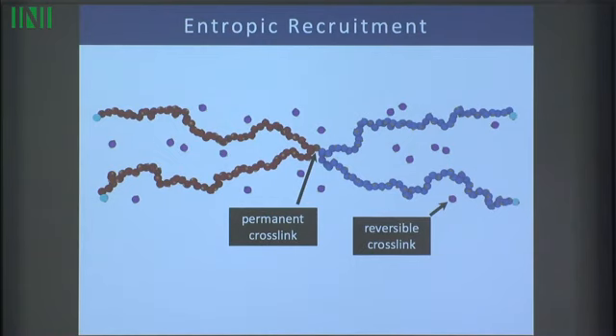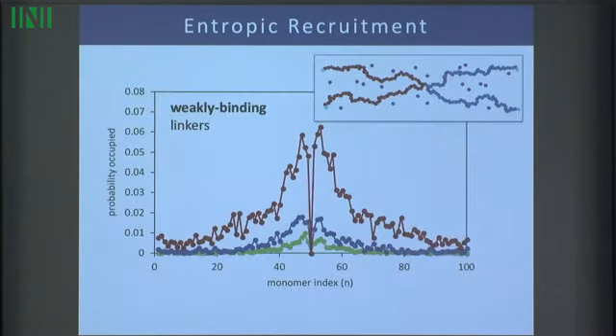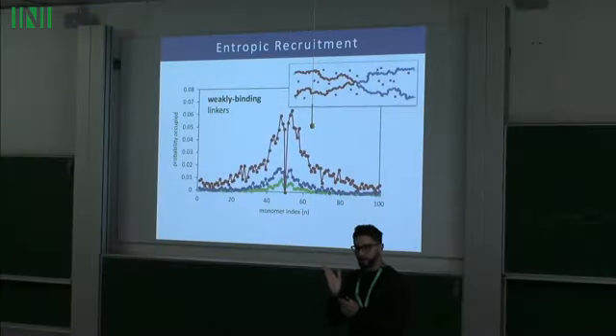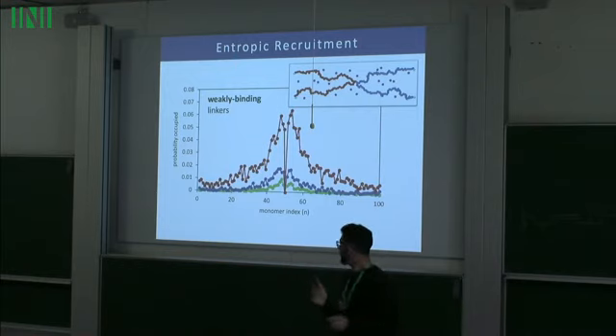It's valence limited. So what we do is we look at the probability that a reversible crosslink makes a bond as a function of the distance from the permanent crosslink. Okay? And so in this plot here, that's the monomer index. So index 50 is the position where I put the permanent crosslink on the two chains. And then position 100 and 0 are the two endpoints of the polymers. And I'm averaging just the chance that I see a bond over the simulation in that system.